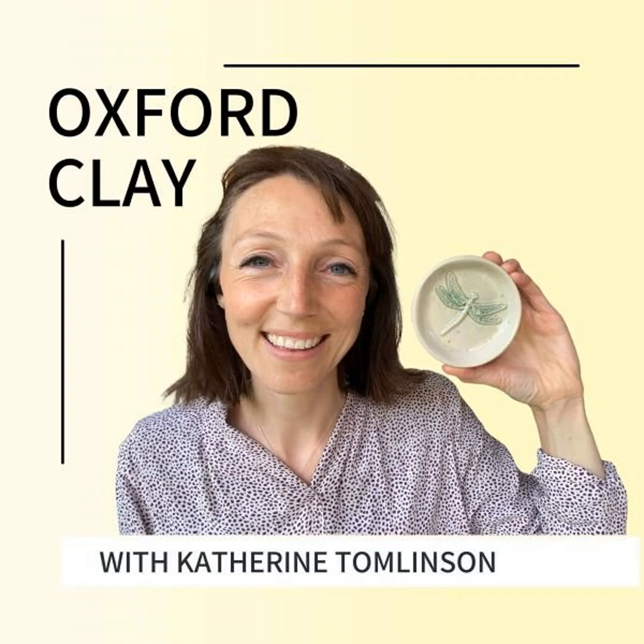your ingredients. You've got the water in there, you've got all the dry powders in there, and you just give it a really, really good mix. It usually takes me probably about 15 minutes of mixing with a paddle mixer to get the clay into a nice smooth consistency. You can then sieve your clay afterwards. Once you think it's all completely mixed, it'll be a lovely liquid. If it seems a bit stiff, I can add a teeny bit more water, but I always make sure that I don't add any more deflocculant, because it's very easy to over-deflocculate your casting slip. When I've done that before, it turns it from a liquid back into a solid again. I haven't found a good way of undoing that process.